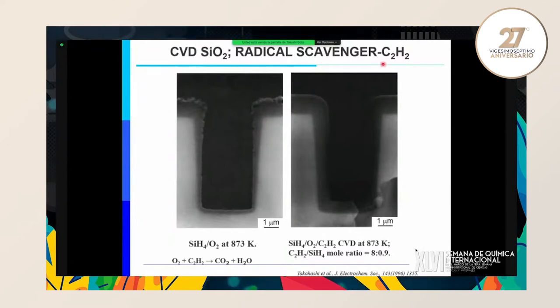So C2H2, acetylene, was discovered as a radical scavenger to eliminate nanoparticles in the gas phase. By adding acetylene, it becomes very smooth, and no nanoparticles deposit on the silica. But in many CVD processes, it is very difficult to find a radical scavenger, even for alumina or silica, which are very important materials. Usually it is too hard to find a good additive scavenger gas to eliminate nanoparticles.